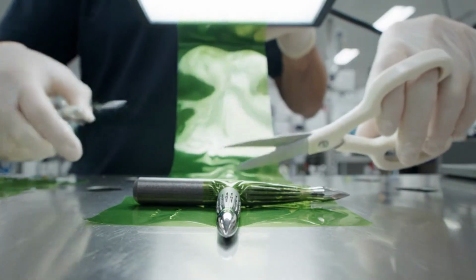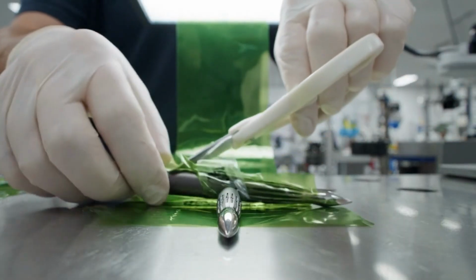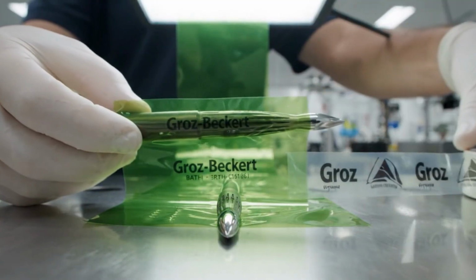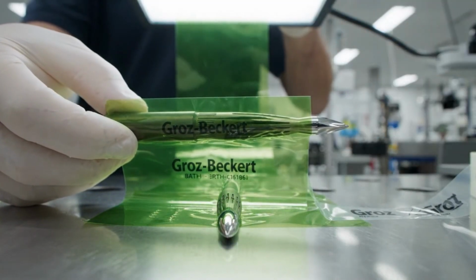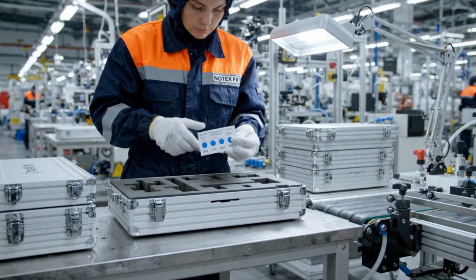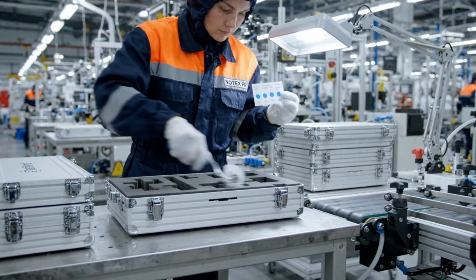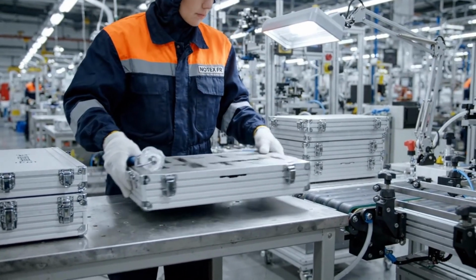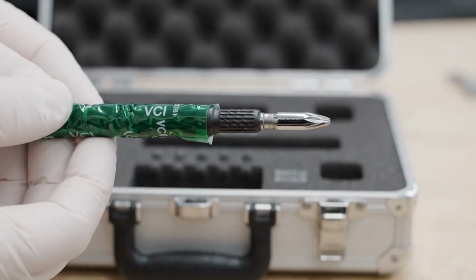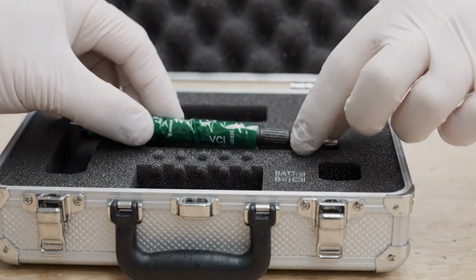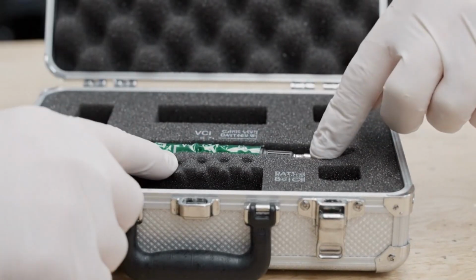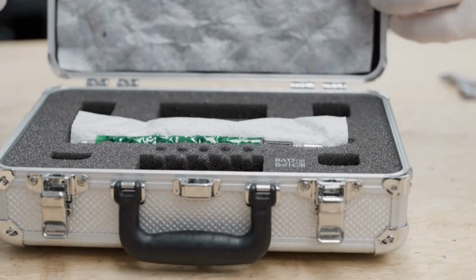The VCI film is impregnated with sodium nitrite and benzotriazole, compounds that vaporize slowly inside the seal. The aluminium case is purged with dry nitrogen before sealing, reducing the internal oxygen content below 1%. The foam insert is cut to within 0.2 of a millimeter of the needle's profile, a fit that ensures the needle will survive a drop.